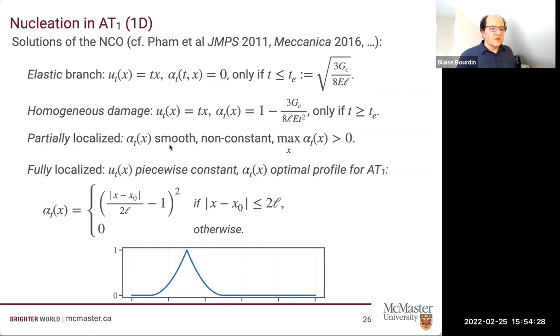Then what I would call partially localized, that is your alpha, your order parameter, is a smooth function, but whose maximum is not 1. And then what I call fully localized, so that would be a function that goes all the way to 1 and back to 0. So that's what we think of as a phase field crack. You see this analysis done in pretty much any paper that's been published since 2010 in the field.